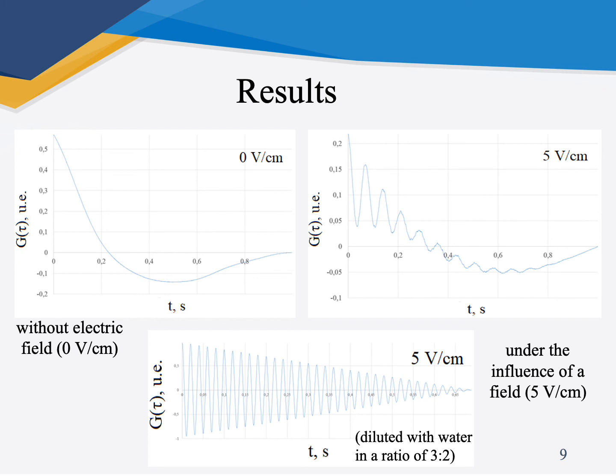From this figure you can see the obtained autocorrelation functions with the applied electric field with strength equal to 0 volts per centimeter and 5 volts per centimeter for fullerenol solutions with different concentrations. In zero electric field, the autocorrelation function has an exponential decay, and with the field at 5 volts per centimeter it becomes a damped oscillation curve, the period of which is proportional to the electrophoretic mobility. Dilution of fullerenol with water provides a more stable picture of the particle motion, reflected by the autocorrelation function, and its period becomes more clearly visible. Therefore, it is most effective to use a slightly diluted solution of fullerenol under the influence of electric fields with a small control voltage.